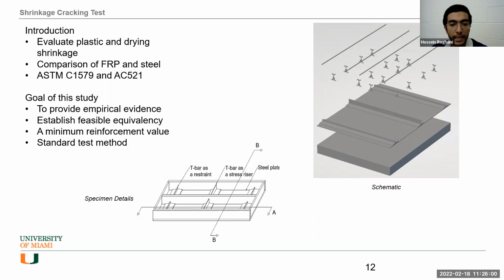But after investigating the shrinkage phenomenon with our specific design of a specimen and the wind tunnel, the environmental conditions, everything, at the end, a reliable and repeatable test which determines the shrinkage crack control of FRP and also the steel reinforcement will be developed. So at the end of the day, hopefully, we can standardize our method as an ASTM test protocol, or maybe as an appendix to the previous ASTM, which was ASTM C1579. Here you can see the details of the specimen.